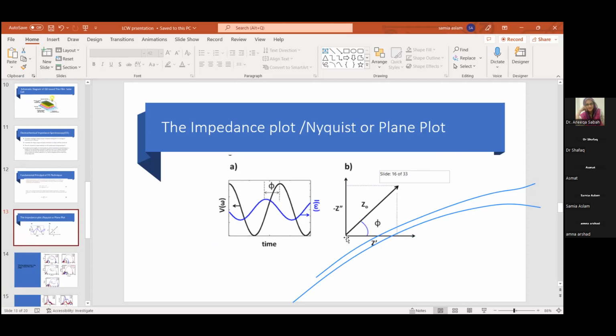Since this impedance is a complex impedance because the circuit is realized as an RC circuit, wherein R is definitely always real. But when we talk about a capacitor, the capacitor offers a phase into the interface, and that phase means that the impedance is actually complex in nature. So it has some phase which is represented by the imaginary part of this complex number, which is the impedance, and secondly, it is represented by a negative sign, which shows that the phase of the capacitor is always negative.